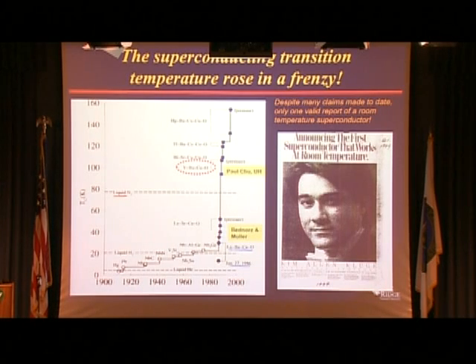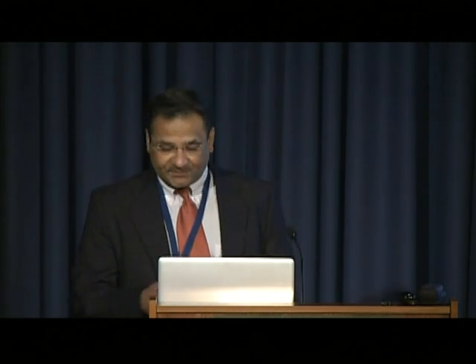Now, despite the fact that the highest temperature superconductor was 140 Kelvin, the superconductor of choice for applications is the 90 Kelvin superconductor, yttrium barium copper oxide. And you may wonder why. And it has to do with the fact that the yttrium barium copper oxide superconductor has far better intrinsic superconducting properties. And that goes back to its crystal structure.